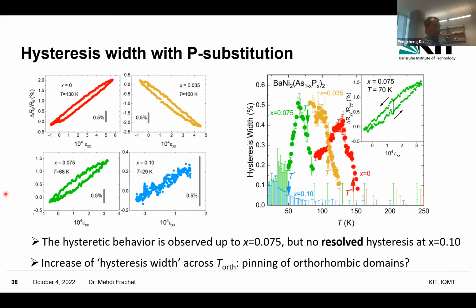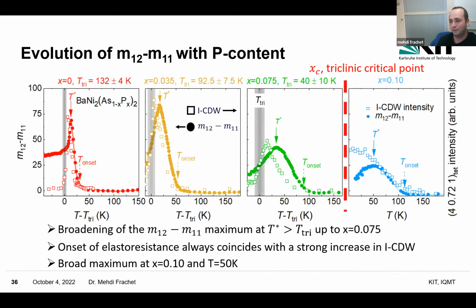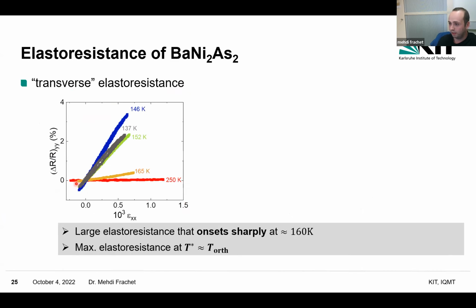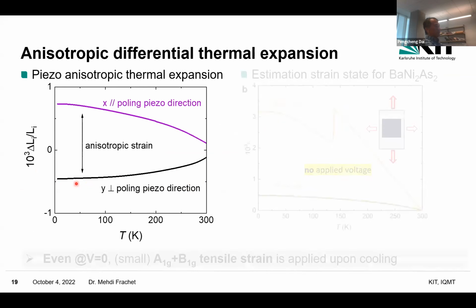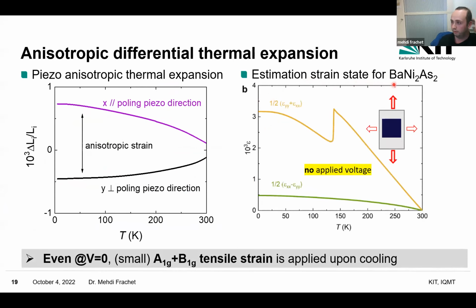So I guess part of the question is, is it close to the true zero strain point during the measurement? Close, yes. It depends how you define close. I can show again the thermal expansion of the piezo. It's pretty good, right? So that's the strain state that we can estimate for barium nickel 2 arsenic 2. You see that we apply the maximum strain we could apply if all the deformation was transmitted from room temperature and we had 100% strain transmission, which is not the case. So that's really an upper limit, I would say.